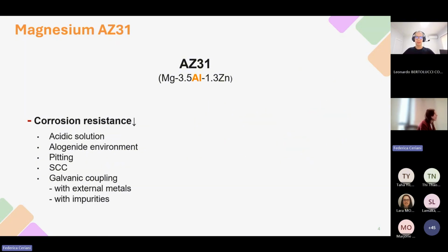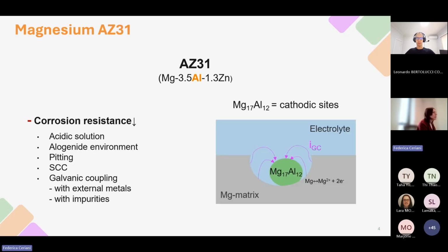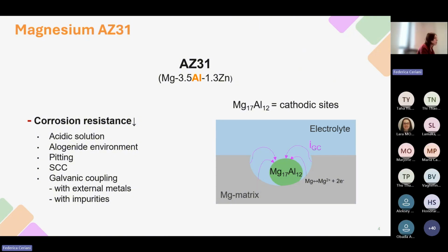Unfortunately, the performance of components made of magnesium AZ31 is compromised by poor corrosion resistance. In particular, this alloy suffers localized corrosion, and pitting, stress corrosion cracking, or galvanic coupling phenomena could take place. Galvanic coupling could occur between the magnesium alloy and external metals, but it could also take place due to the presence of impurities, or even because of intermetallic precipitates within the alloy itself. Indeed, these precipitates behave as cathodic sites, leading to the localized corrosion of the surrounding anodic magnesium matrix.